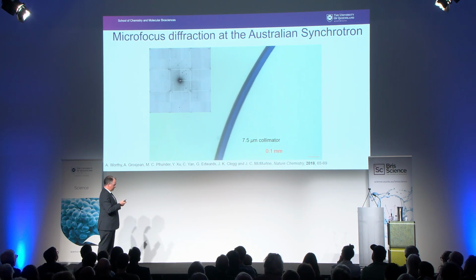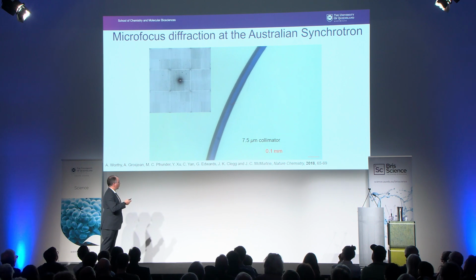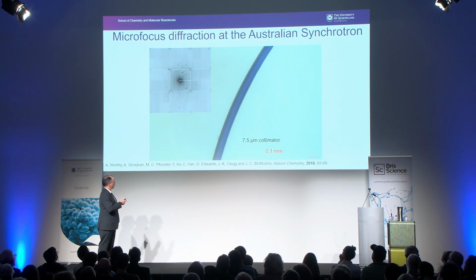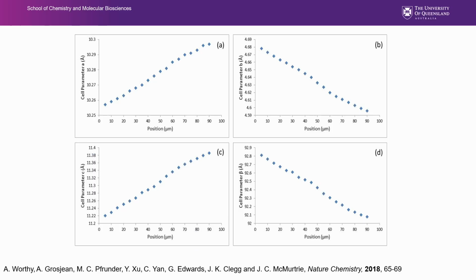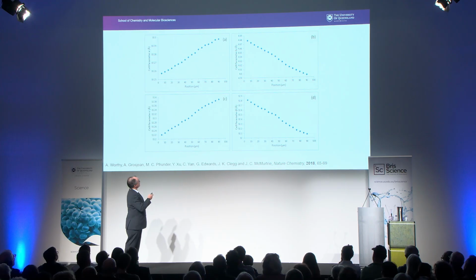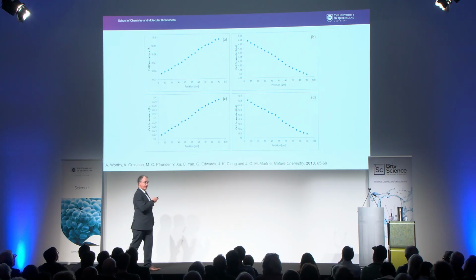The nice part about this is it allows us to work out what's happening at each position within the crystal. And so we can determine the crystal structure throughout, or how the crystal structure changes throughout the bent region of the crystal. So here's just some of that data. And what we can see here, as we move from the outside of the crystal to the inside, remembering that the B-axis runs up the length of the crystal, we see that the crystal gets shorter on the inside and longer on the outside.